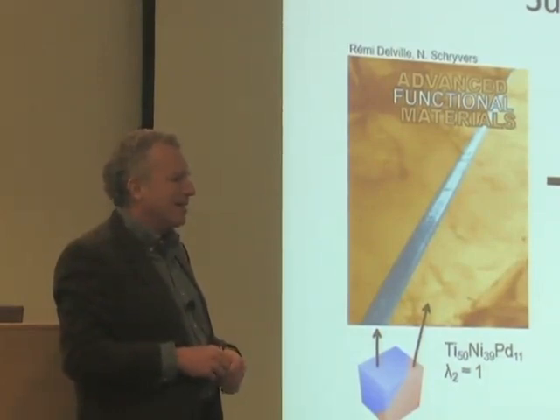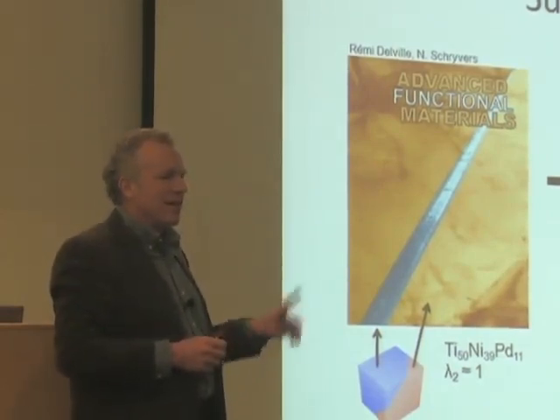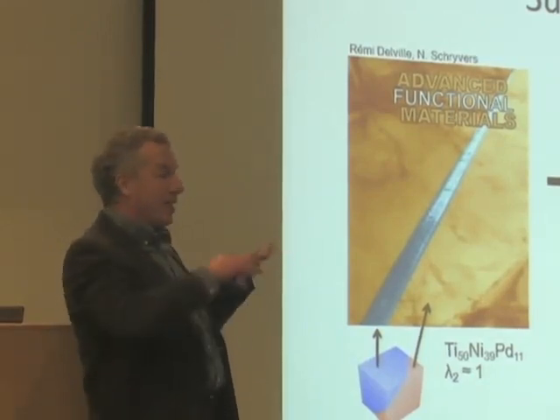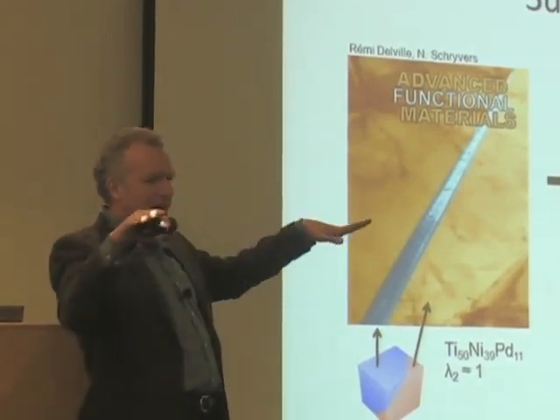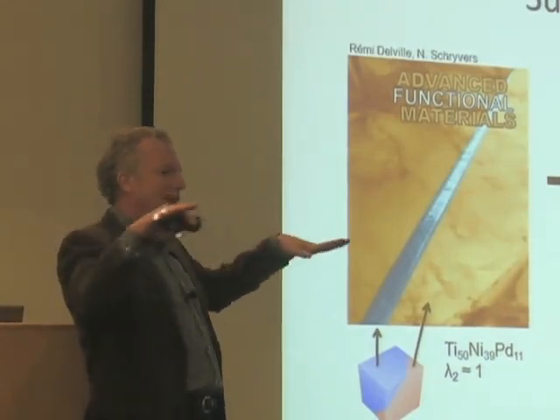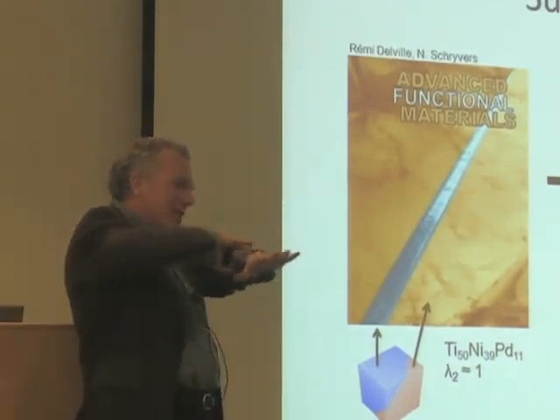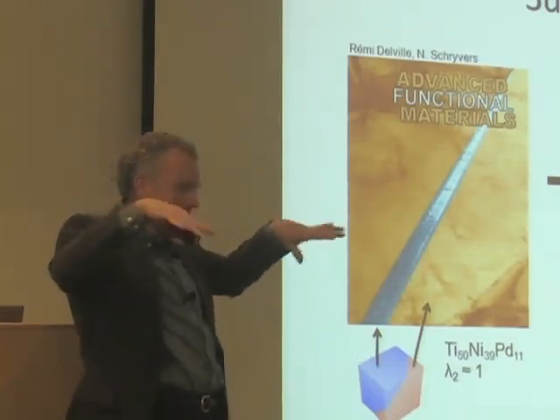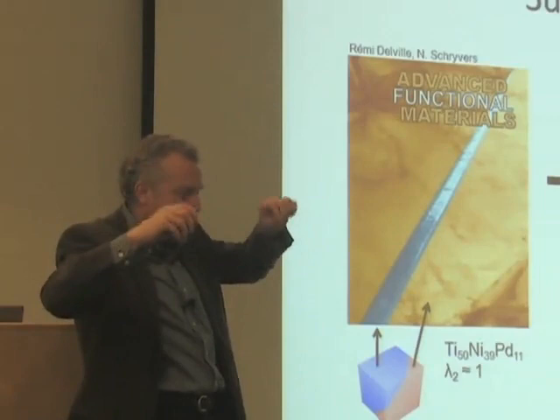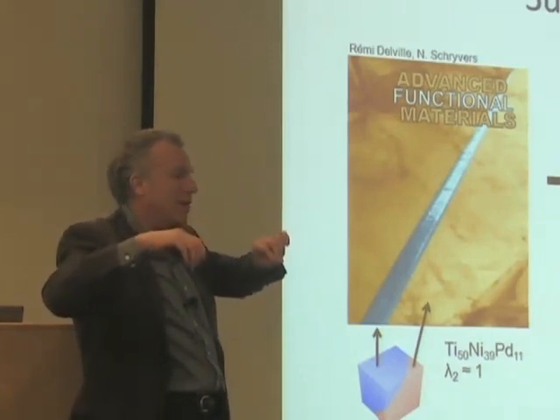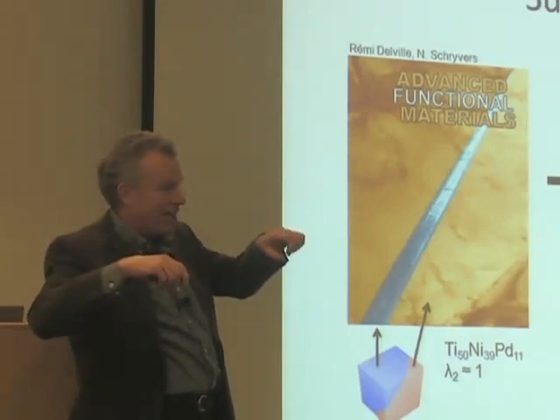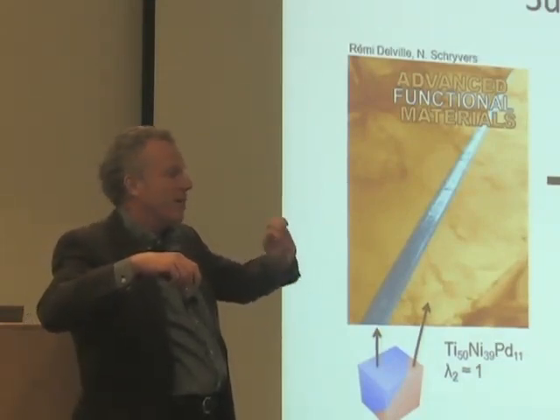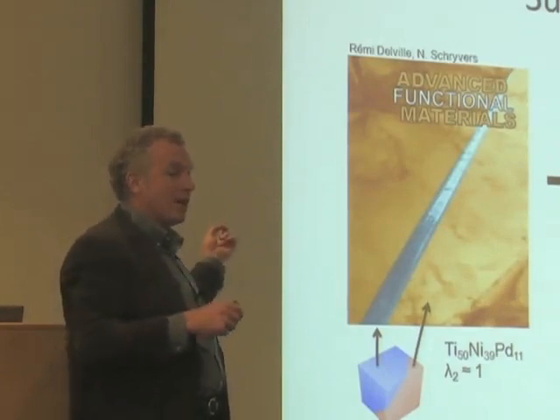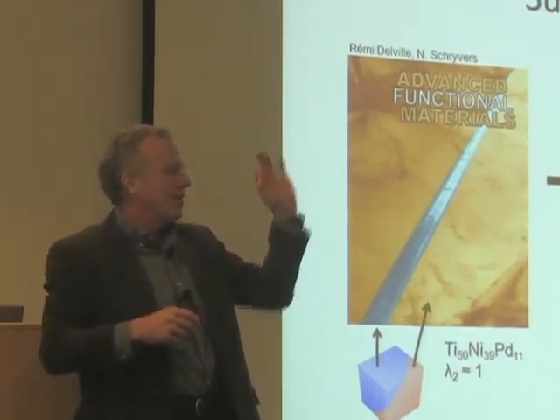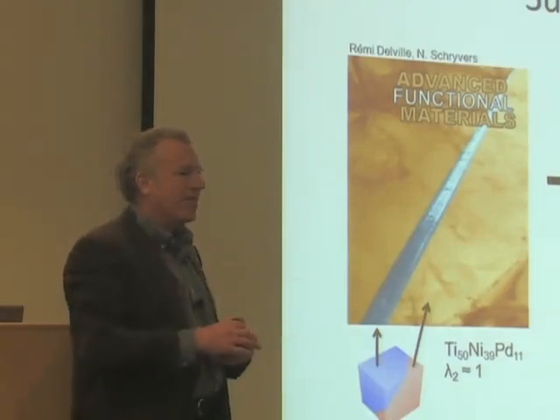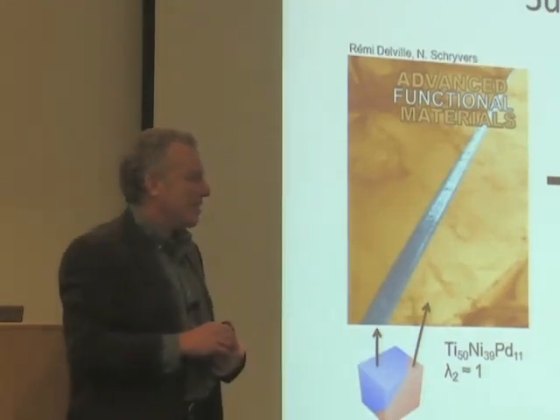The combi was done in a film setting. They're sputtered films, so they're on the order of a few microns thick. And then they're diced up. You know, there's the kind of compositional gradient. They're diced up, and then each one is addressed with X-rays for the lattice parameter measurements. But even on that scale, the dicing is much larger than the grain size. The grain size is on the order of the thickness. And then the bulk samples, those are arc melted buttons, 1 centimeter, and the grain size is probably a few microns, something like that. So they're all polycrystals, so there are many of these interfaces inside there.